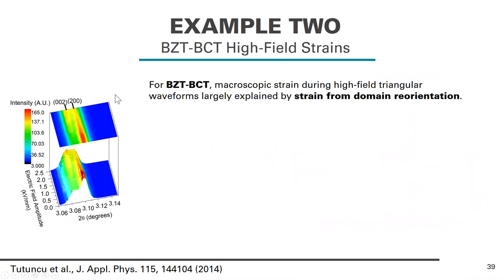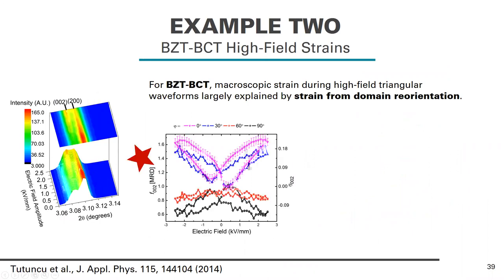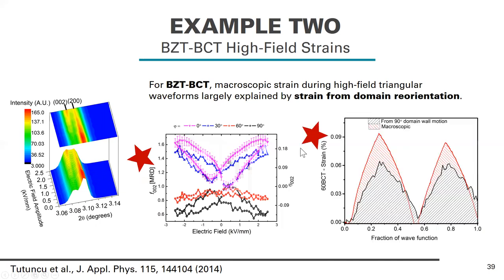In a second example, I go back to this BZT-BCT example. And in this material, the raw data over here on the left was shown before. And although I didn't show you on the previous slide, we actually measured the degree of domain switching as a function of angle to the electric field. And that data is represented here in this middle plot. Once again, we have F on one axis and eta on the other, because they're related.